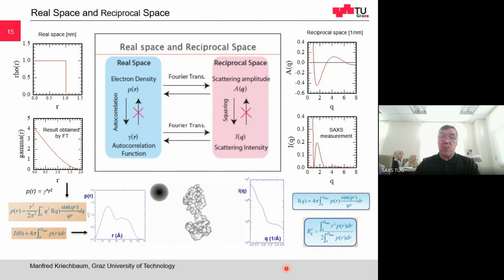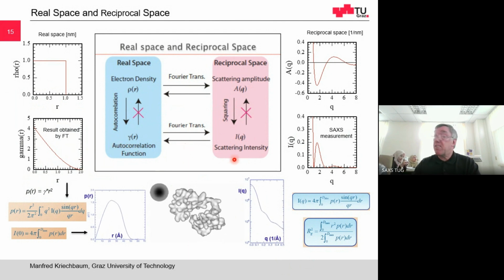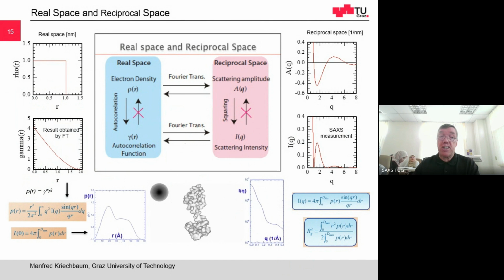This is now a more complex slide. You start here in the reciprocal space. So you have your scattering pattern. And how do we get into the real space? You have to do a Fourier transformation to get your one-dimensional P of R function. So by Fourier transformation of the scattering curve, you get your P of R function.